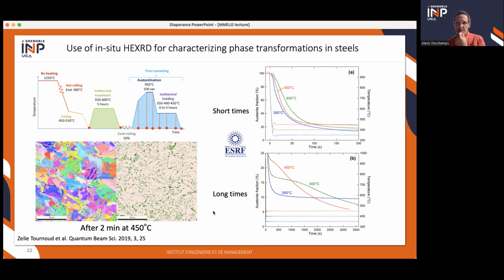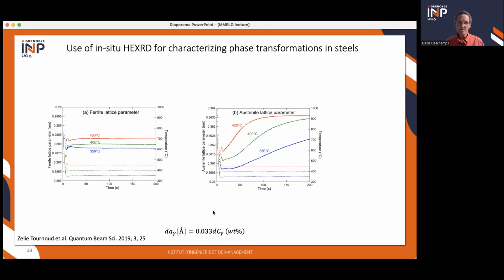The additional information you can have from the diffraction patterns is the lattice parameter. And during these transformations, the ferrite lattice parameter is more or less constant, and we made the approximation that there was little carbon supersaturation in ferrite in this case. Whereas the austenite lattice parameter is evolving quite a lot. And this is the indication at constant temperature that you have a carbon enrichment.